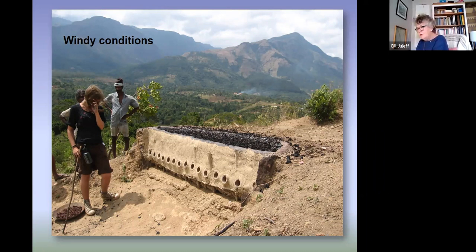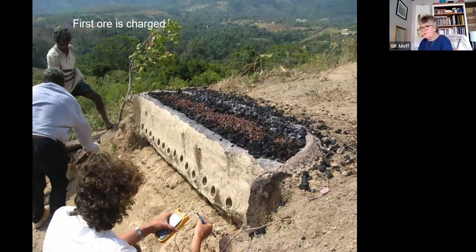So this is what it looks like when we put the first iron ore in the top, on top of the burning charcoal. And that is replenished all the way through the smelt. So we were using anything up to, no, much more, 200 kilos of charcoal per smelt and 100 kilos of iron ore. So we keep replenishing that over 6 to 8 hours. The thing to note here, amongst the engineers and the scientists, is the scorching on the top of this front wall. There's very clear scorching, which you don't see to the same extent on the back wall. We'll see more of that as we go through.